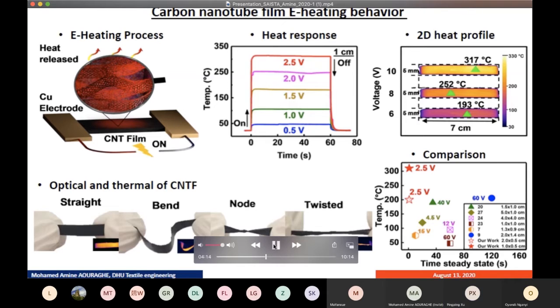Here is the 2D profile of heat distribution on the CNT film surface, which shows an even distribution of heat on the CNT film. In comparison with other materials made so far, such as e-heating nanowire composites and graphene, the proposed CNT film can generate high temperature within a few seconds and at a low voltage of 2.5 volts. As an application of the thermal conversion of CNT film, we have made a composite based on CNT film and PDMS to make an electrothermal actuator.